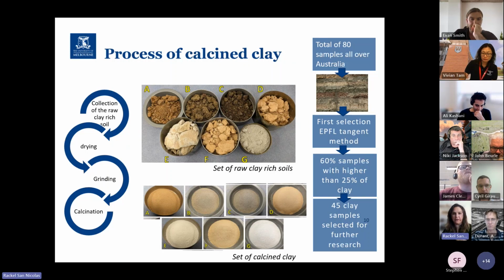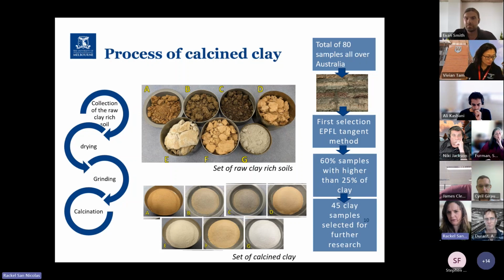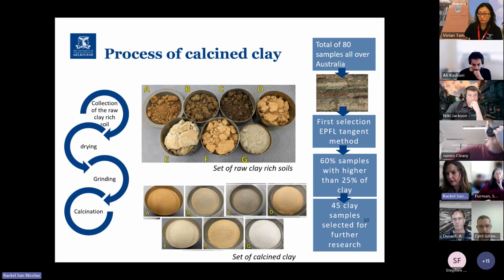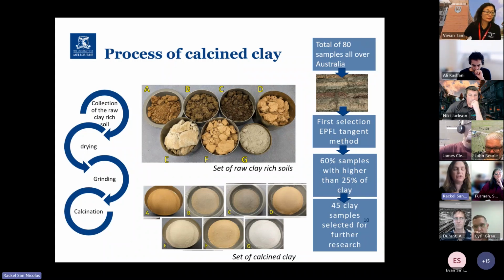I just put some pictures of some of the samples that we have, which are real samples that we have collected from different quarries and how they look after. So you've got a range of color, and I'm not going to talk too much about color, but that might be a point as well later on. Just for you to be aware, at the moment we've got data on around 80 samples overall in Australia of different clay that has been analyzed. We usually push them through a screening analysis with different methods in order to see if there is enough clay in those clay-rich soils, because there is usually sand and other types of material mixed in. About 60% of those 80 samples have enough clay in the sample to be taken further and to be analyzed.